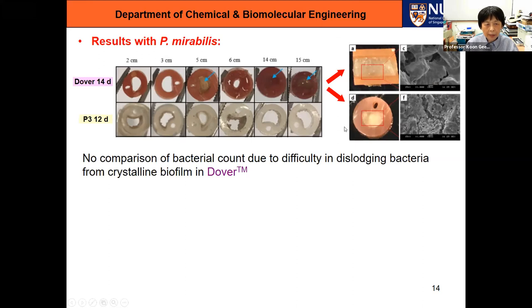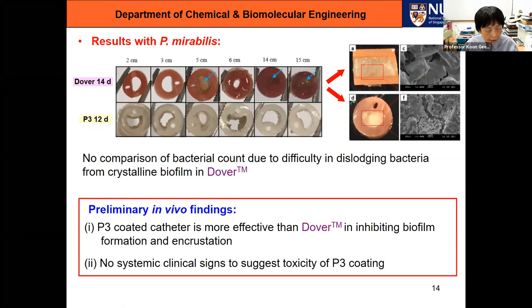We tried to compare the bacterial count, but we couldn't because the bacteria embedded in these crystalline biofilms is very hard to dislodge using our method of sonication and so on. If you compare the P3, there are some deposits, but definitely the lumen remains open much more than the Dover catheter. So from our preliminary findings, we can conclude that the P3 looks like it's more effective than the Dover catheter in inhibiting biofilm formation as well as encrustation. And there are no systemic signs to suggest that this coating will cause cytotoxicity to the animal.